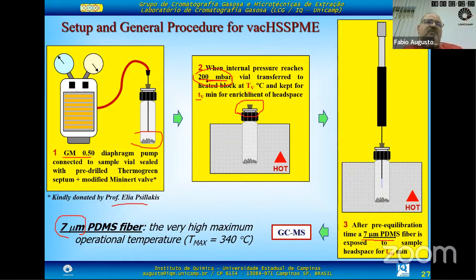If we reduce more, we're going to check it. Perhaps the difficulty of manipulating such a low pressure environment would not result in such a high improvement. For example, a lower pressure would demand special vials with thick glass walls, because the vial can explode with the pressure. We need to use a better seal here, and the improvement would not be that large.